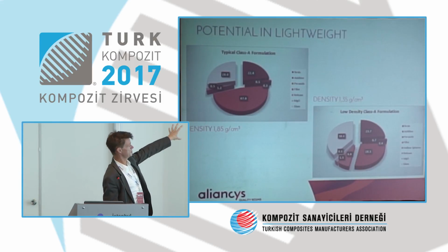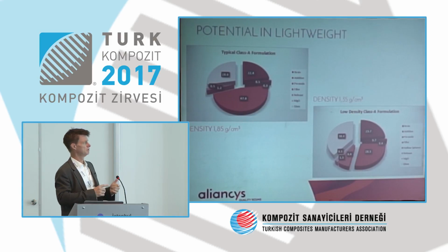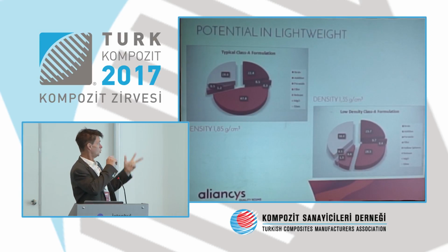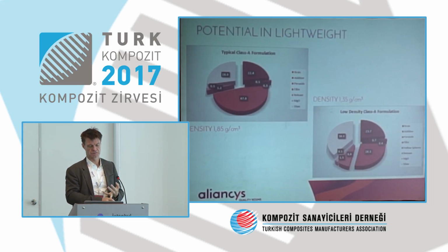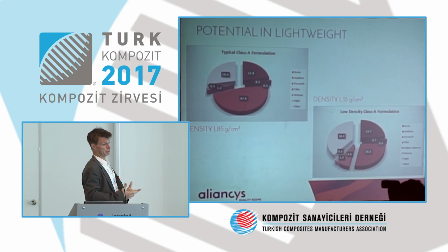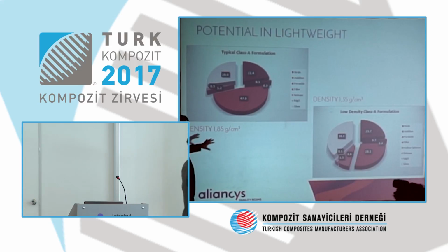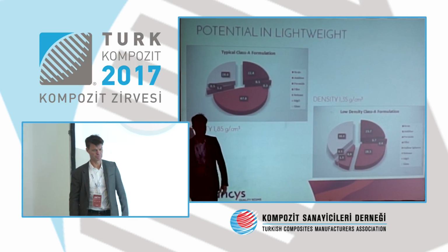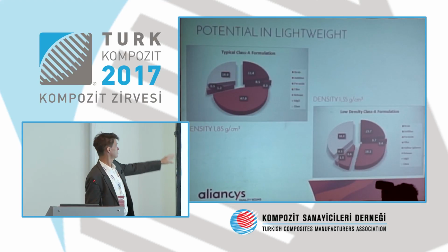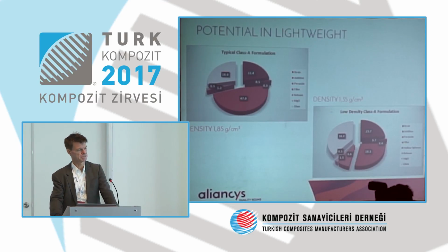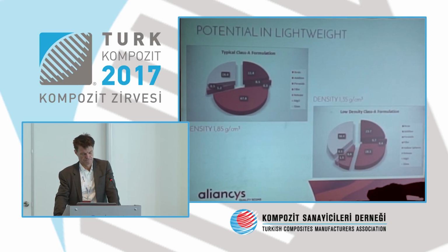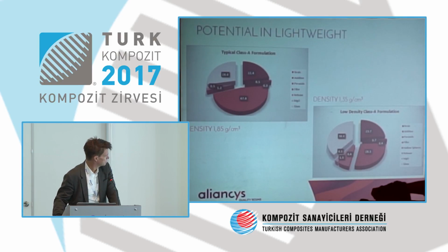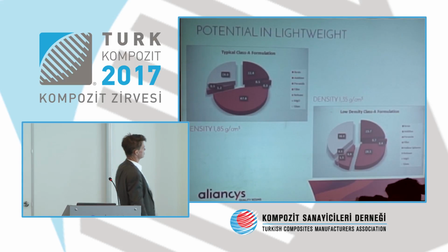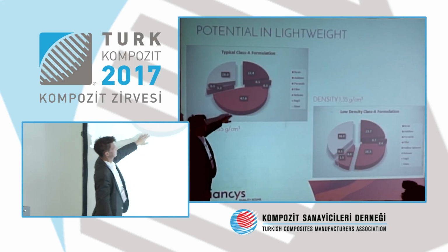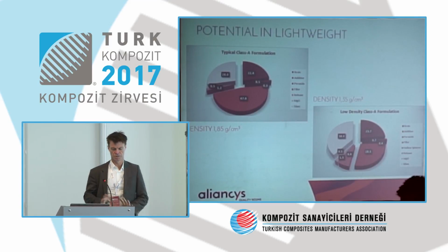Then you see a typical formulation for Class A, which consists of resin, additives, low-profile additives are already in, peroxide. You have also the filler component, which is a solid material which cannot shrink intrinsically. So this is the major part with about 47%. And about 28 or 25% is basically glass. And the cheapest raw material used is, let's say here, the calcium carbonate filler. And you can play with this.